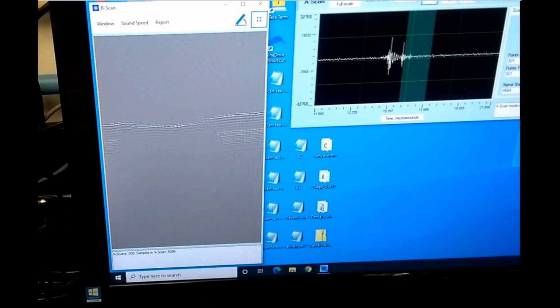Above the surface is just water, so there are no reflections and the B scan shows a purely gray area. Below the surface, we can start to get a better understanding of the sample's structure. The lines below the surface extend on the ends, but have a missing section in the middle. This is caused by the spot weld nugget. In this B scan from another sample, we are able to detect a reflected area within the nugget itself, likely caused by a bubble or an area of porosity.